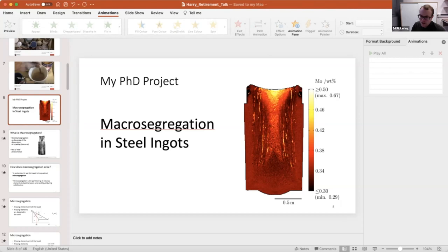So there's a question from Suresh about the capability of accepting predictable heterogeneity in castings at a different length scale and eliminating the need for homogenization. So yeah, we of course never really homogenize the ingots. They're forged for hundreds of hours potentially, or held at above 1200 for hundreds of hours, but actually even the dendrite arm spacing is too coarse. So you might be talking secondary dendrite arm spacings of like a millimeter, 2 millimeters, something like that. So even there, they're really too coarse to homogenize properly.